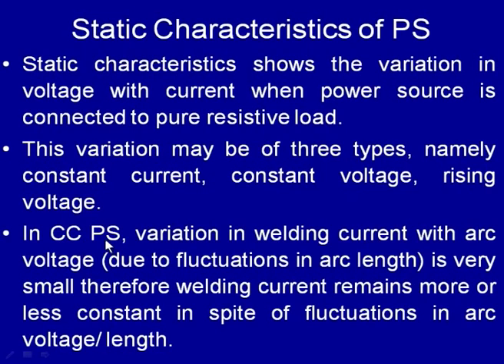In the constant current type of power source, that is the CC power source, PS for power source, the variation in the welding current with the arc voltage due to the fluctuation in arc length, if it is occurring, is very small. So, the main thing associated with this is that the welding current fluctuates very little even with the fluctuation in the arc length. Therefore, the welding current remains more or less constant in spite of the fluctuation in the arc voltage or the arc length.